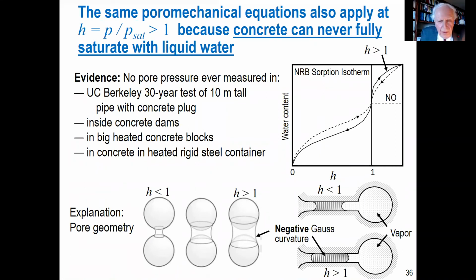Then one point I would like to emphasize, which is typically overlooked, and there are no test data unfortunately for it, is that when we come to saturation and increase the pressure, the isotherm is not flat. It would be essentially flat if concrete were filled by liquid. Then you could use the equation of state for water from steam tables, and you would predict a negligible slope because water is quite stiff by comparison. What is in reality, it goes up very steeply, probably as steeply as it does here. Of course, it's all irreversible, mainly with geometrical effects.